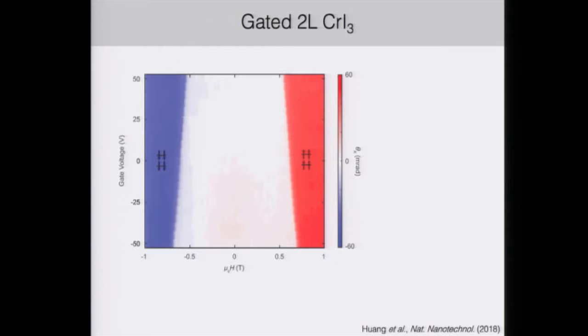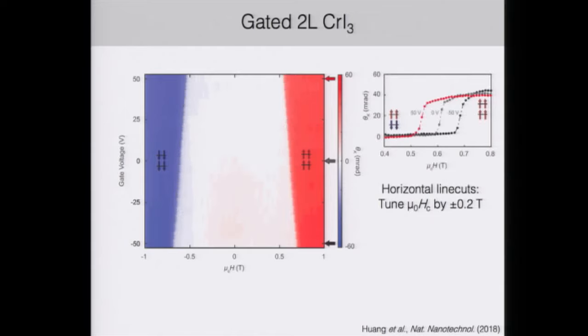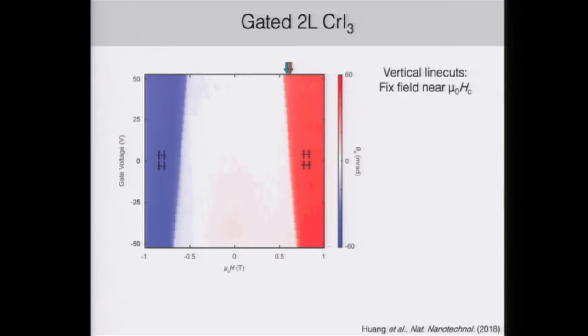If we apply a single gate voltage, we're able to change the transition in this material. So we're able to linearly tune this field of transition with the gate voltage. If we look at the horizontal line cuts in this plot, that shows us that we have tunability by about plus or minus 0.2 Tesla. What's more interesting is if you look at the vertical line cuts.